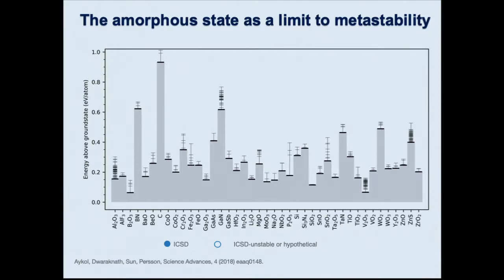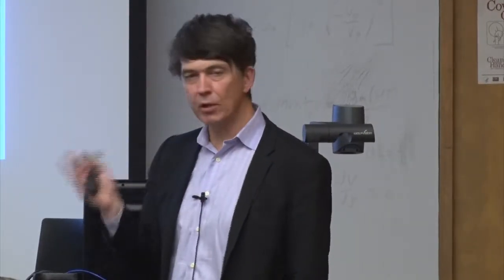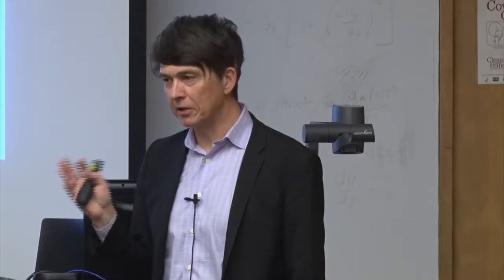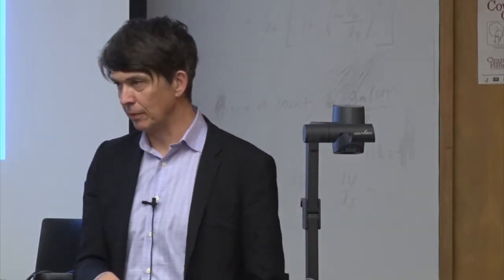Okay, so what we roughly figured out was that most metastable compounds are within about 100 millielectron volt above the ground state. What Kristin Persson's group did is to try to come up with a more chemistry-specific limit. They started with the hypothesis that maybe the amorphous state is an upper limit for metastability. The reasoning roughly goes like, well, a material can always go amorphous if it wants to, if it's already in the mixed state, but it can't always crystallize in a structure. So they just wanted to test that.